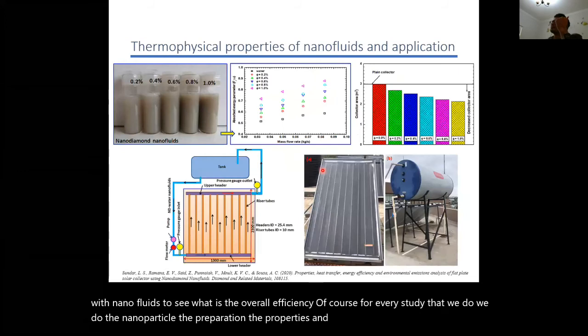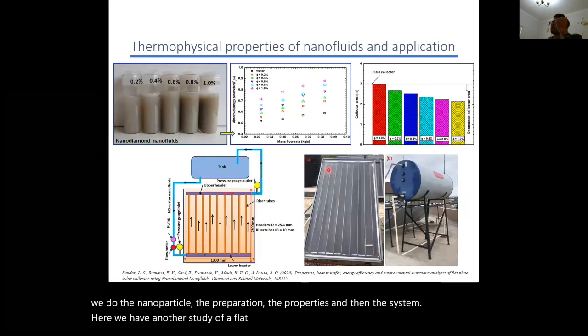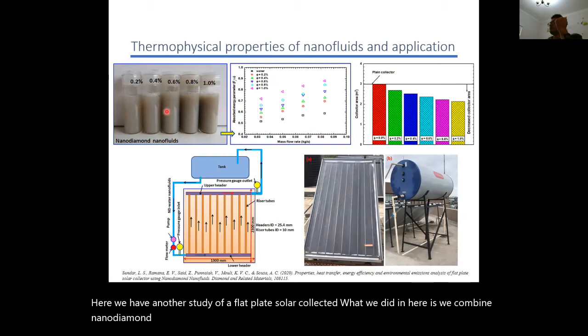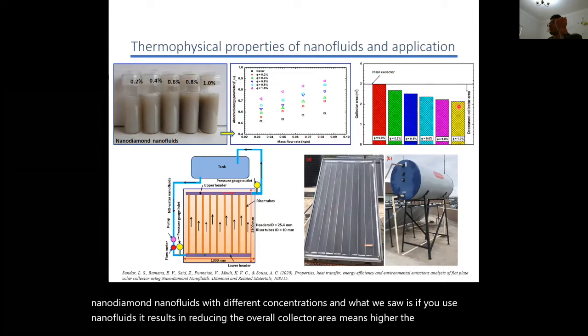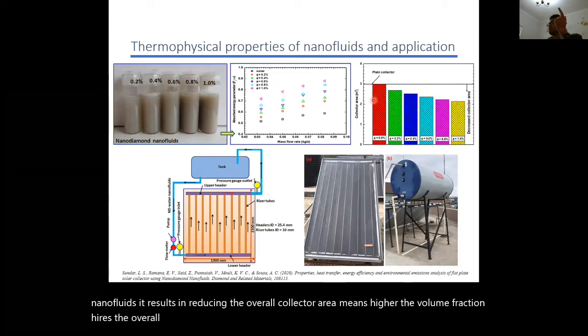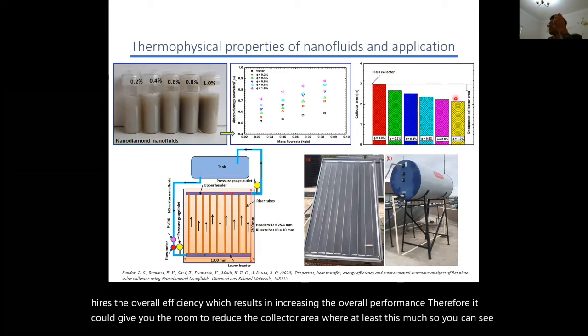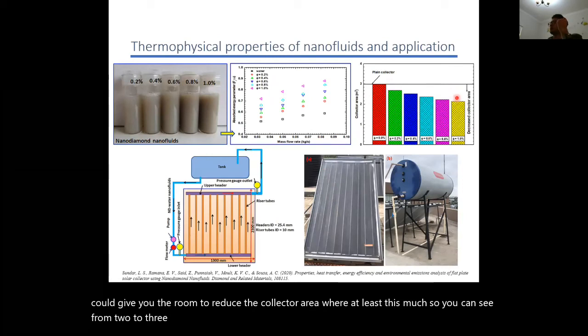Here we have another study, of a flat plate solar collector. What we did here is combine nanodiamond nanofluids with different concentrations. And what we saw is that using nanofluids results in reducing the overall collector area. It means the higher the volume fraction, the higher the overall efficiency, which results in increasing the overall performance. Therefore, it could give you the room to reduce the collector area by at least this much. You can see from 2 to 3 meters, or about 1 square meter, you can reduce this.